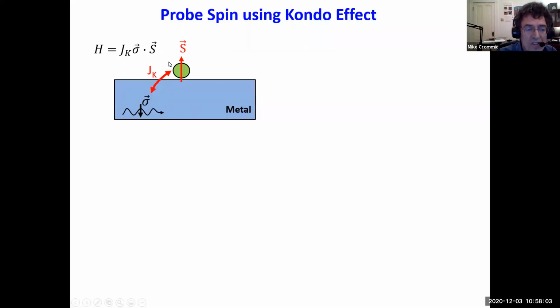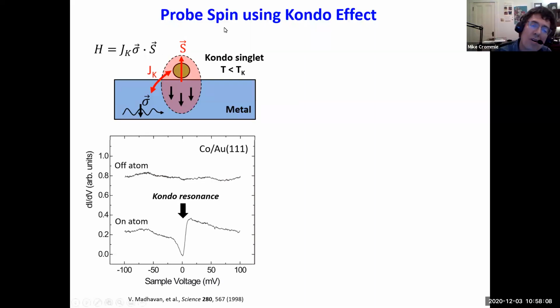electron with this exchange coupling, and that causes a many-body singlet to form, where essentially you can think of the local moment as capturing an electron from the metal, which then screens the local moment. It's actually a many-body screening cloud. And the characteristic of this many-body screening cloud is that you get a Kondo resonance in the local density of states at 0 energy. And that resonance can be a Fano resonance, where it can be either a peak or a dip, depending on details. And here we were able to observe this many years ago in my group, looking at cobalt atoms on gold.